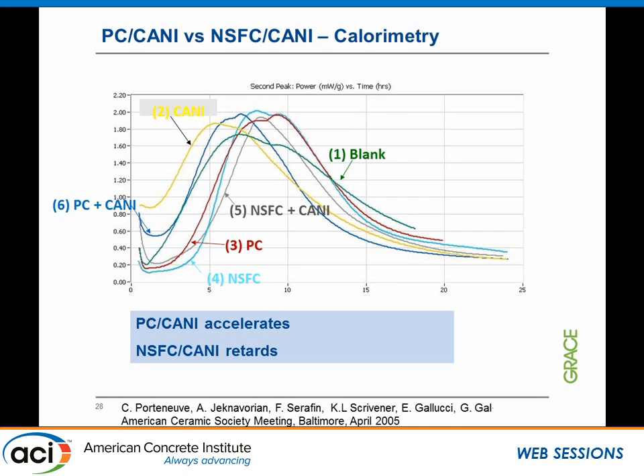But when we added the accelerator with the naphthalene sulfonate, you continue to see this retardation, which cannot be corrected. But when you put the polycarboxylate with the calcium nitrite together, definitely you do see the acceleration.